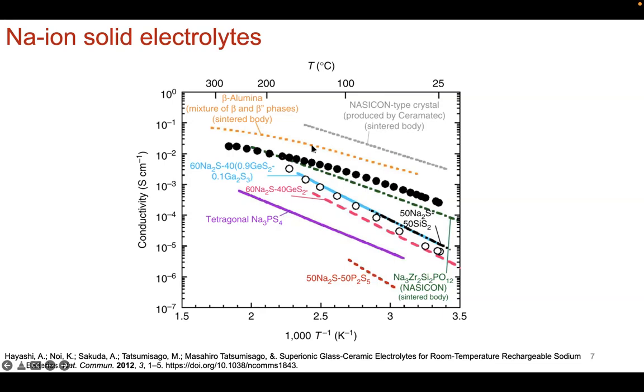Now, with sodium ion solid electrolytes, what you'll see is a lot of work has been done in the thiophosphate-based compounds. There's been a lot of literature that's come out in the last 5 years on these types of compounds, right? And there's been a lot of focus also on improving their ion conductivity just by changing the crystal structure. So stabilizing a high temperature, high ion conductivity phase at lower temperature through synthetic methods, and that we've seen with the lithium ion solid electrolytes as well, right?